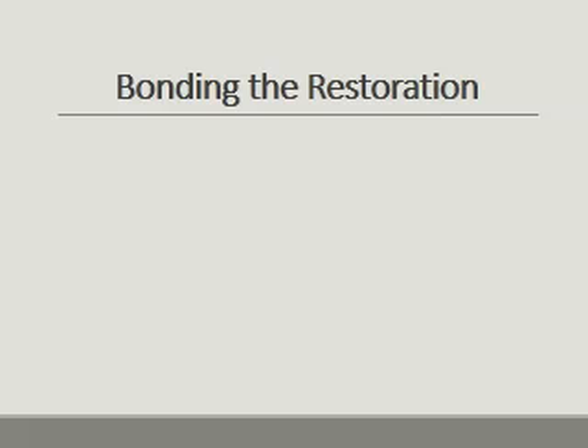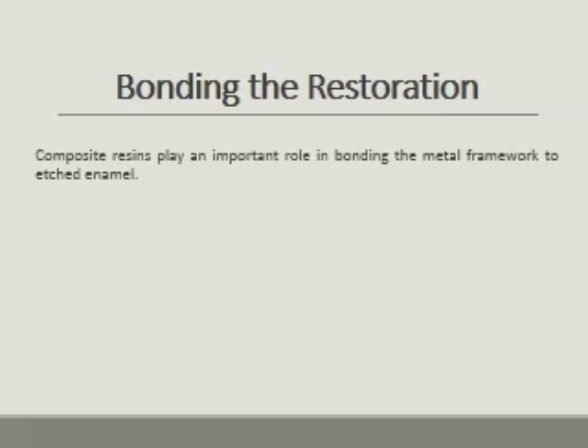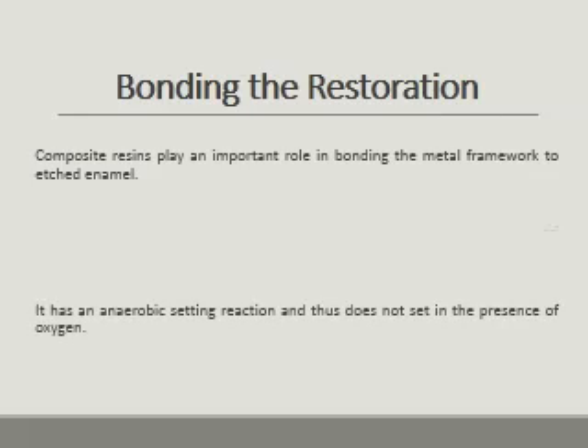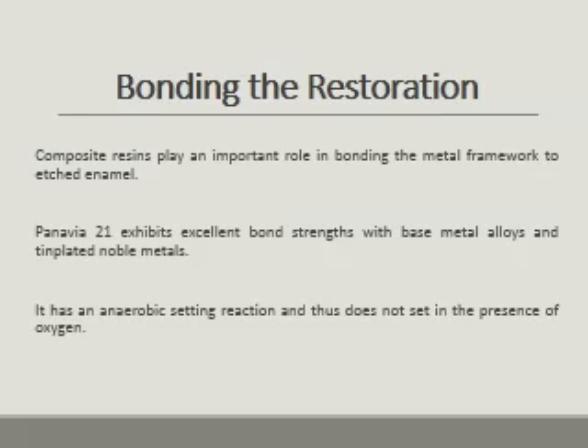Bonding the restoration. Composite resin plays an important role in bonding the metal framework to the enamel. Panavia 21 exhibits excellent bond strength with base metal alloys and tin-plated noble metals. It has an anaerobic setting reaction and thus does not set in the presence of oxygen. There is the Oxyguard, which is applied over the restoration after cementation to prevent oxygen and to make the environment anaerobic for complete setting.